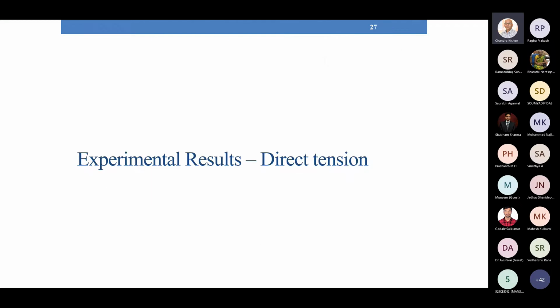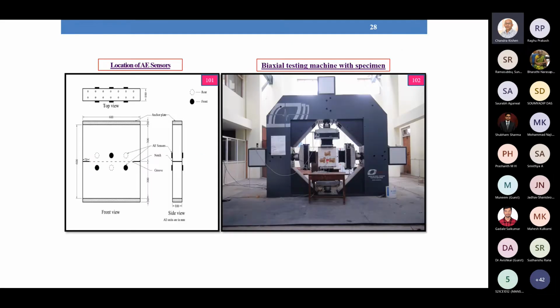Now I'll show you some of the experiments from direct tension. This is our biaxial fatigue testing machine. You can see the size of this machine with respect to this wall; this is the roof level and this is the first floor level. We have 4 actuators which can be independently controlled, and we have a specimen which is loaded here. The specimen is a concrete specimen with 2 notches, and performing a direct tension test on concrete is really difficult.